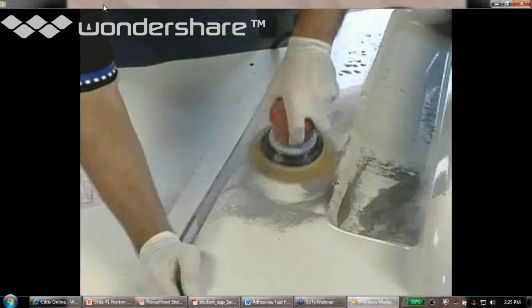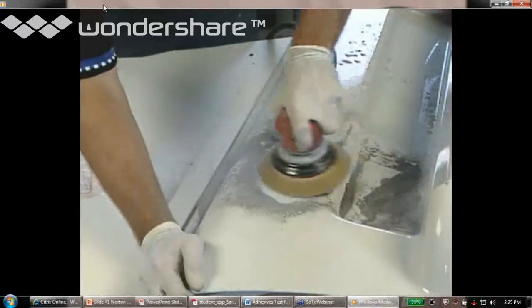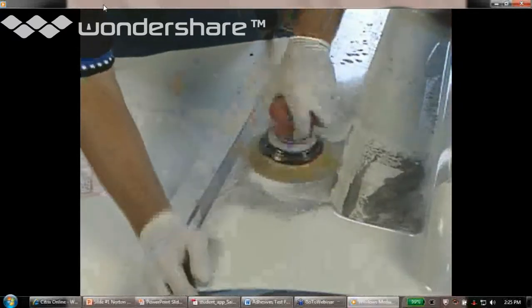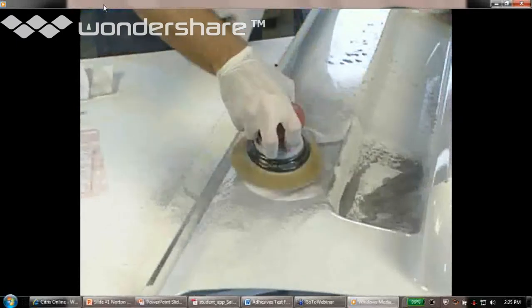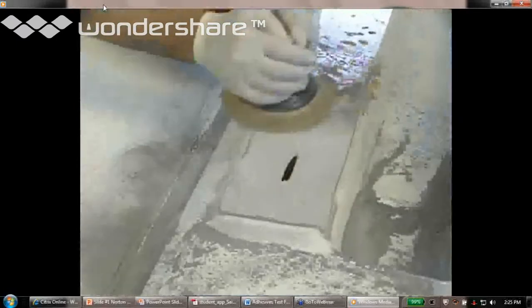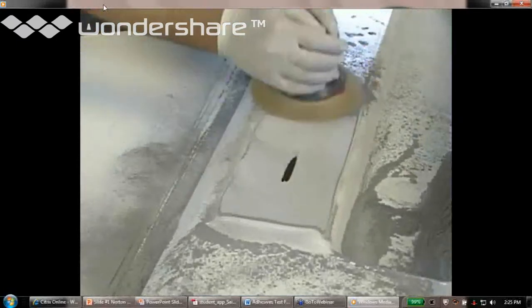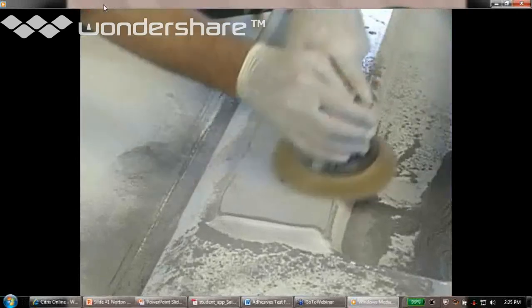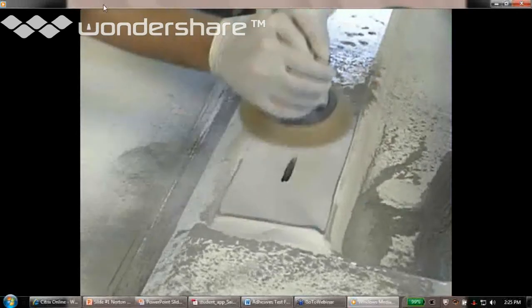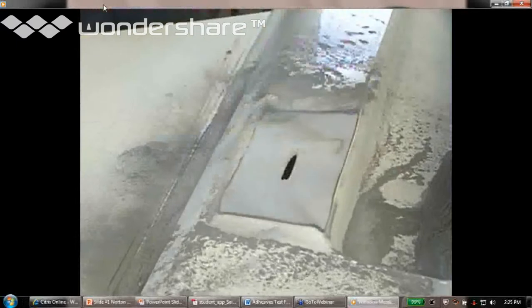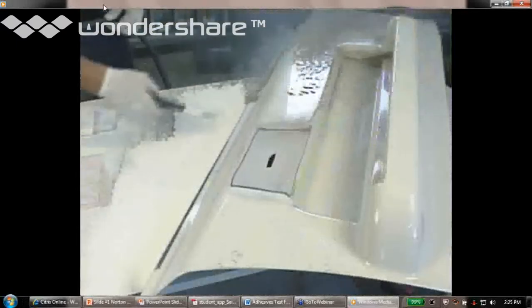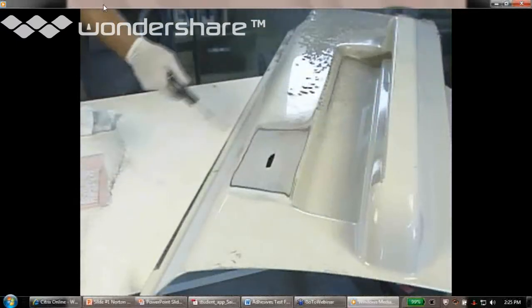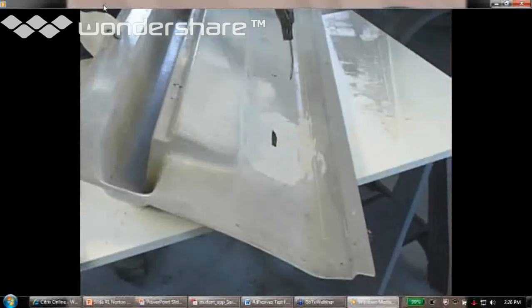Using a DA sander operating at low RPM, sand the front area. Make sure you feather the edges out and that the edges are smooth. Notice that the material powders as you sand. That means this is not TPO plastic, so TPO adhesion promoter will not be used. Use only clean, dry air and blow the surface free of dirt. Do not use a solvent or cleaner.